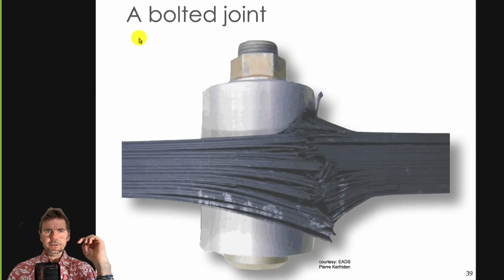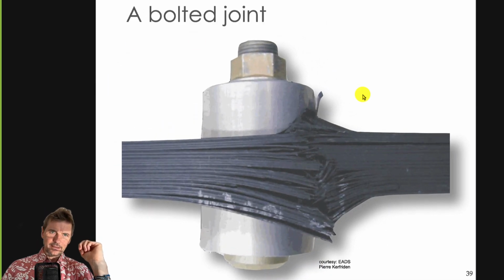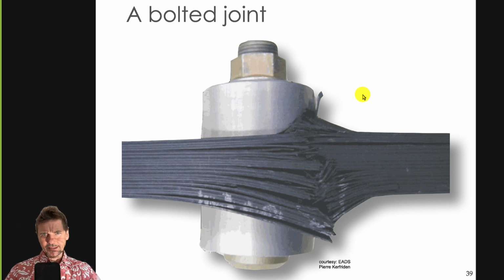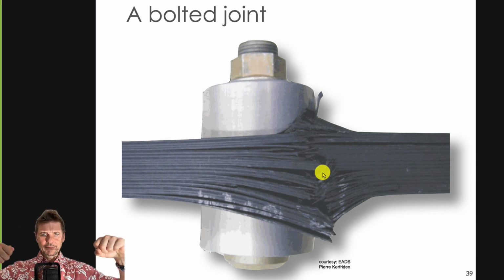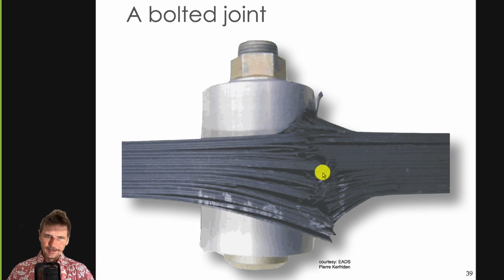So now let's look at numbers. If you take a bolted joint from an Airbus A380, for example, you have a mixture of metal and these carbon fiber composites which are here. And when these things fail, this is what it looks like. So not very nice. You have delamination, debonding, you have the fibers that get loose and get pulled out of the matrix. So these things are extremely negative, of course, and they are detrimental to the life of the structure, so you would like to be able to predict this.